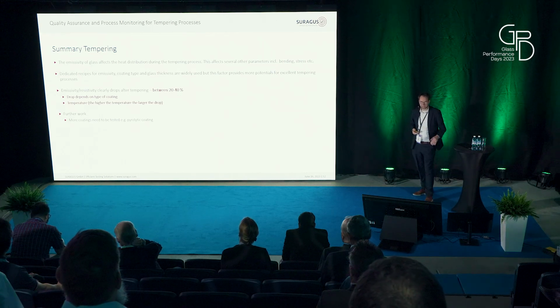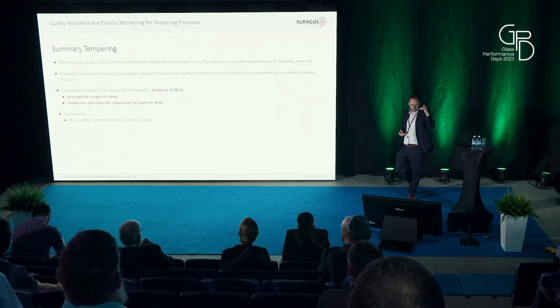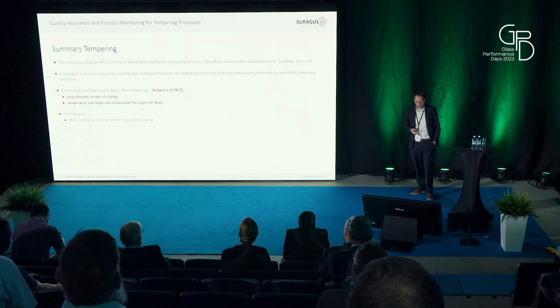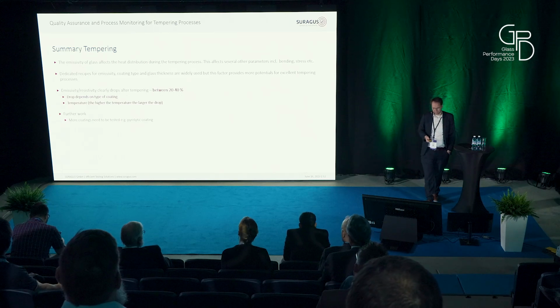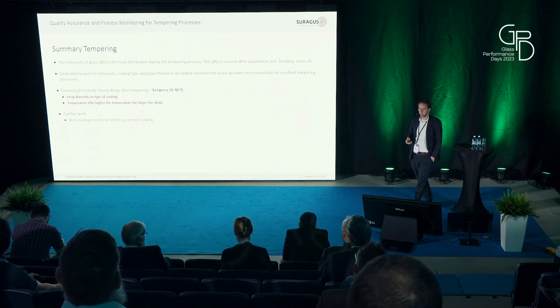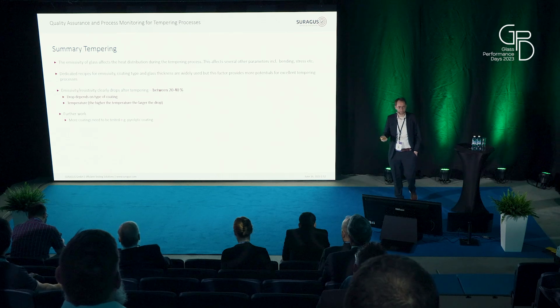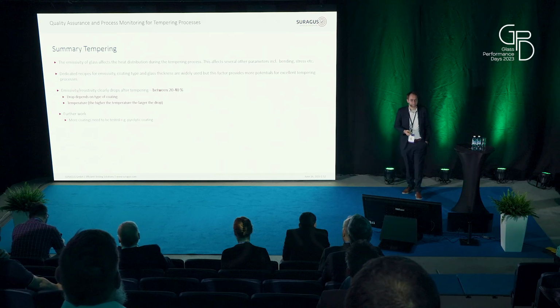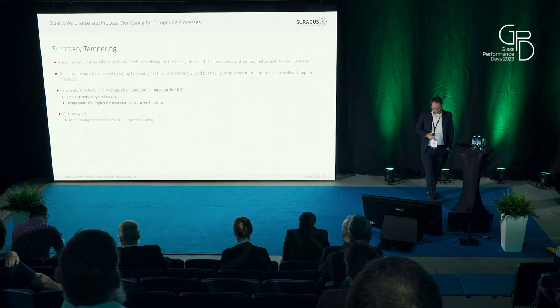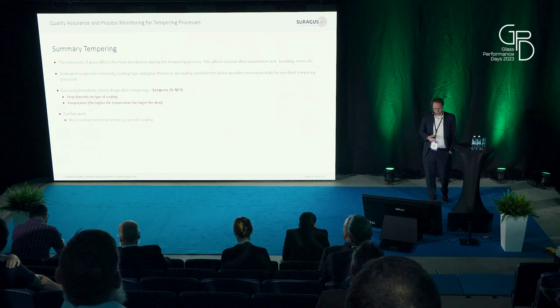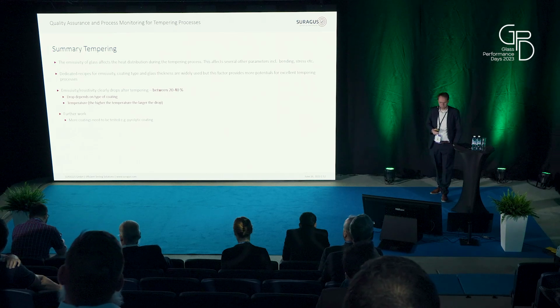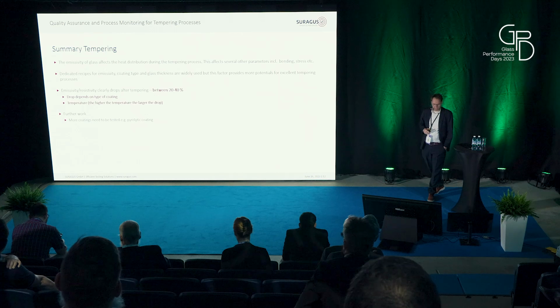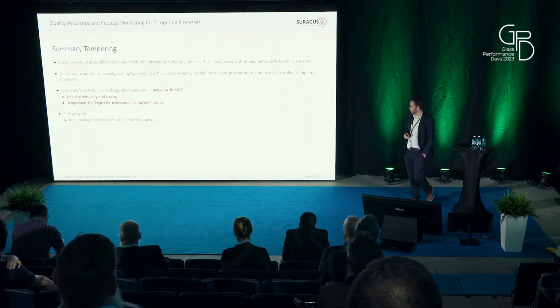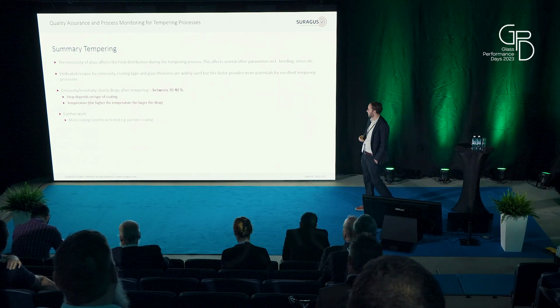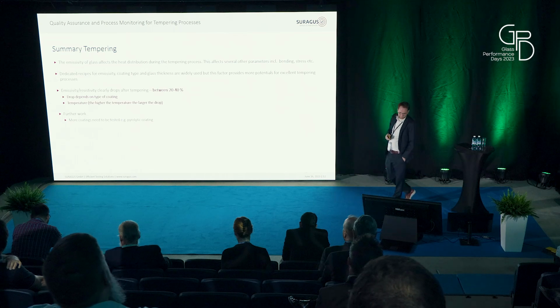So it makes a difference whether the glass has 3.7 or 3.9 sheet resistance before, and this can be measured, and it can also be helpful when new glass is run on a tempering furnace to find the first recipes. Then we saw that the emissivity changes are quite high. The variation is 10 to 40%. We also want to look at pyrolytic coatings at some point. We haven't done that yet. And so this is about the tempering.